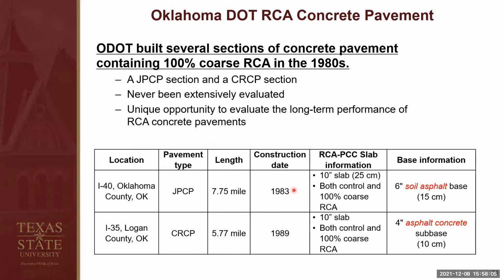And the construction time was about 30 to 40 years ago for both sections. And for both sections, we have a control section aligned with the RCA section. This is really good news because we can directly compare the performance of the RCA concrete with the control concrete pavements. For the base information, I-40, which is the JPCP section, had a soil asphalt base, which was very weak, as I will show you in the later slides. And the CRCP was built on a very solid asphalt concrete layer, and the asphalt concrete thickness was 4 inches.